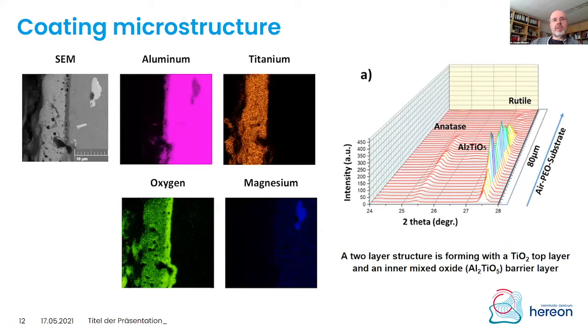And that I would like to show you in the coating microstructure, which you see here. On the left, you see the SEM picture. The top layer is the titanium dioxide. Then comes an interface layer, which is a mixed oxide between aluminium oxide and titanium dioxide. And you see this clearly also in the mapping: there is a layer that is rich in oxygen, the bright green one. And in between, we have the titanium dioxide layer on top and this interface layer that contains aluminium.